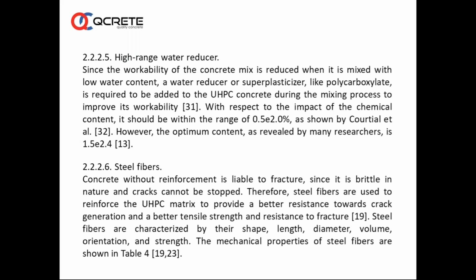In UHPC, you use high range water reducing admixture. Now, polycarboxylic ether based admixtures are available. Extremely advanced admixtures are available, which can be used in very high dosages without affecting the setting time of concrete. Even at very high dosages, these admixtures are tailor-made in such a way that they don't disturb the hydration process or setting time, and hence they are part and parcel of ultra high performance concrete.